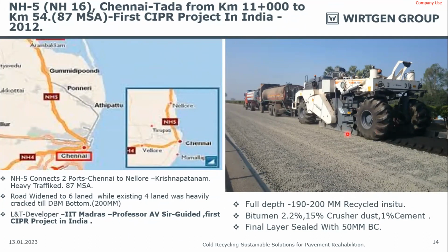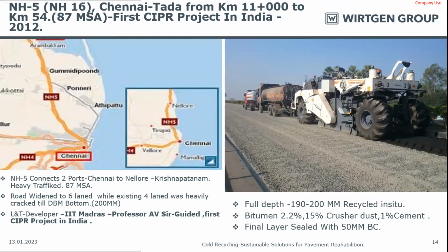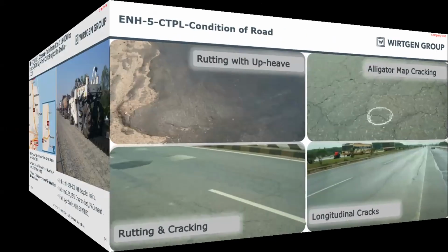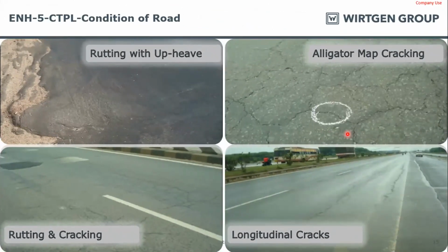So here we recycled the asphalt layer up to a depth of 190 to 200 mm in situ. We required 2.2% of bitumen as binder, and we added 15% of crusher dust and 1% of cement as filler. The final layer was laid as a 50 mm BC layer. And this was designed for traffic of 87 MSA. Here are some job site pictures. So this was the condition of the road before recycling.